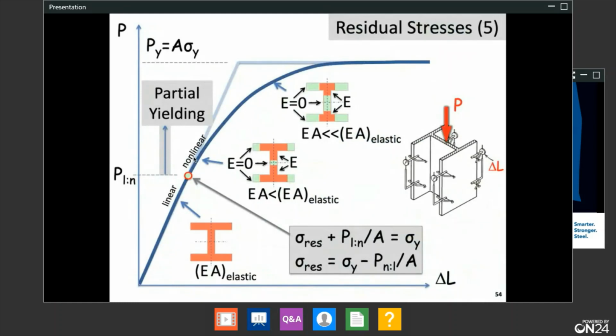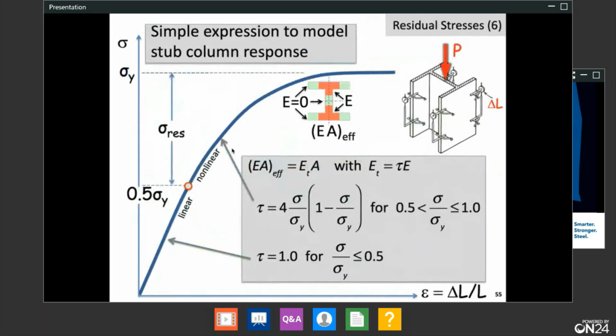These residual stresses cause yielding to occur much earlier, and that's not necessarily a good thing, because once you get some partial yielding, you're losing stiffness quite quickly. So now this is a stub column test, and I'm plotting on the horizontal axis the squash, the change in length of the column. Upper right is the stub column itself. And so I've got this normal strain in the column, and on the vertical axis I'm plotting the stress, and because those residual stresses are there, we will get a nonlinear response curve.